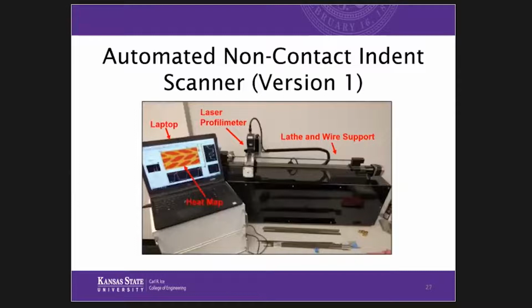Okay, automated non-contact indent scanning. This is version 1 of an indent scanner that we developed. This is actually the first more professional version. We had tabletop things that we had started back in 2011. What this is, we take an indented wire, put it in the machine and press a button, and it automatically scans the wire. We actually take physical measurements of the wire.